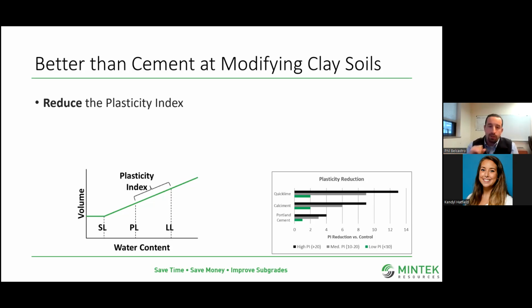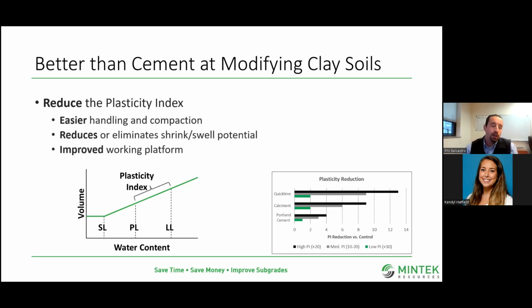And then the green there, the low plasticity, there's not much difference between the two, but you figure, hey, we're already below 10 there. You can only really reduce that plasticity so much anyway. Those are probably already some pretty good soils as long as they're dry and around optimum moisture content. So we've talked about some of this stuff before in other webinars, but the benefits of modification really are, we're going to have easier compaction. We're going to reduce or eliminate that shrink swell potential and really give us a better overall working platform.